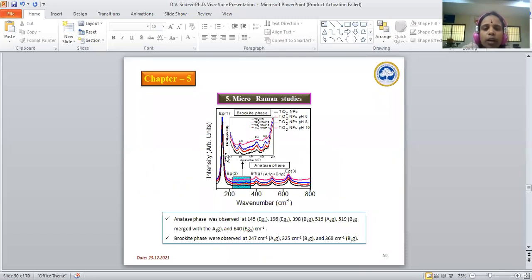This slide shows micro-Raman spectra of TiO2 nanoparticles at various pH levels. The anatase phase was observed at 145, 196, 398, 516, 519, and 640 cm⁻¹. Likewise, the brookite phase was observed at 247, 325, and 368 cm⁻¹, which is shown in the inset figure of the micro-Raman spectra. This data is in good agreement with the powder XRD experiment.